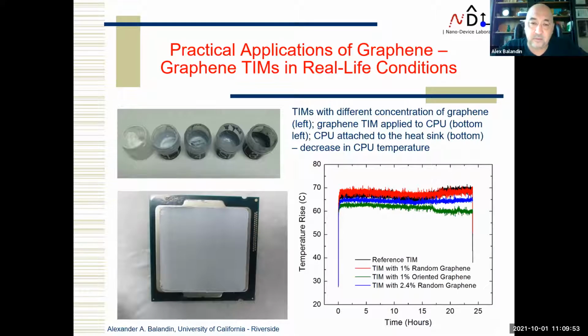And just to give you a few examples, this is non-cured thermal paste, which we used with some advanced Intel CPU, some desktop. By removing the commercial thermal paste and putting in our thermal paste with graphene, we were able to decrease the CPU temperature by 10 degrees Celsius.